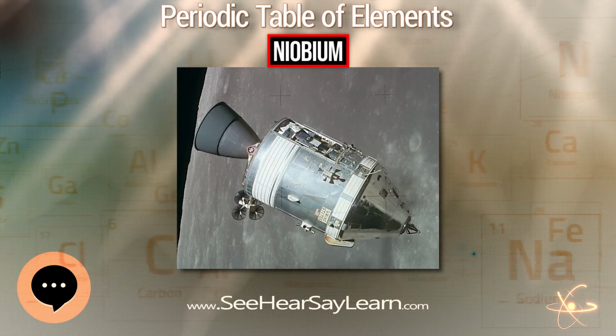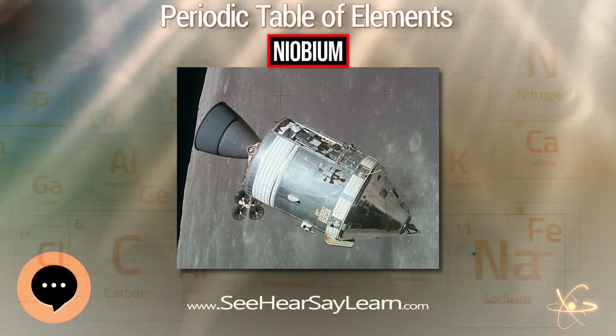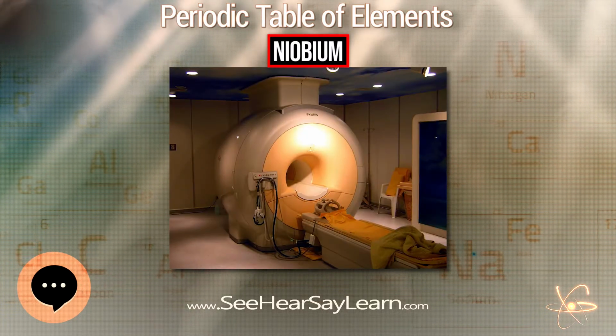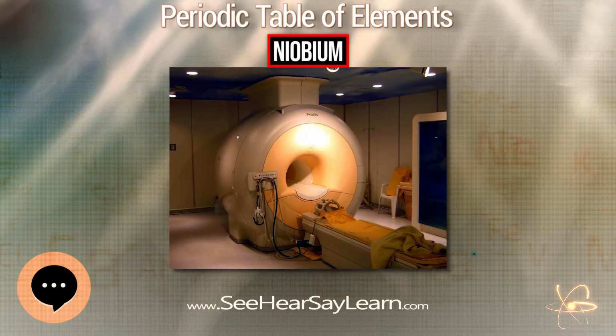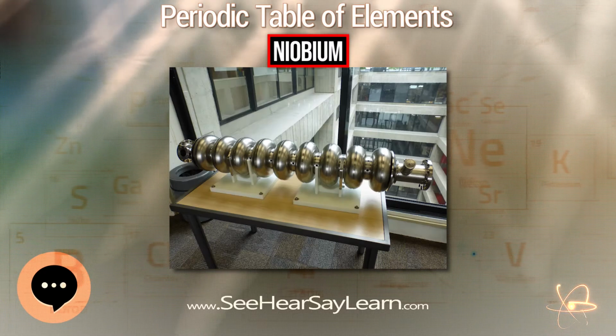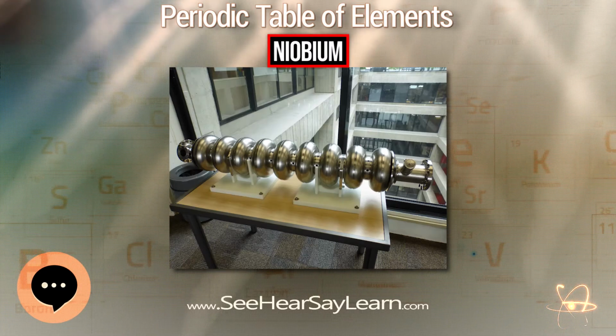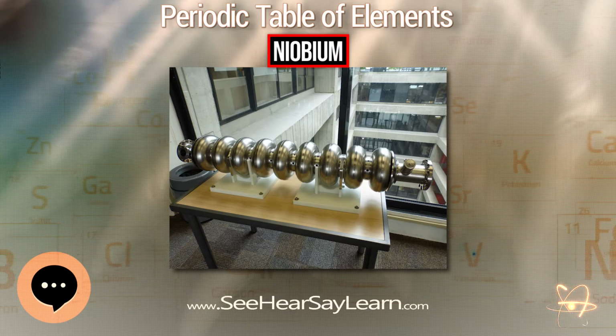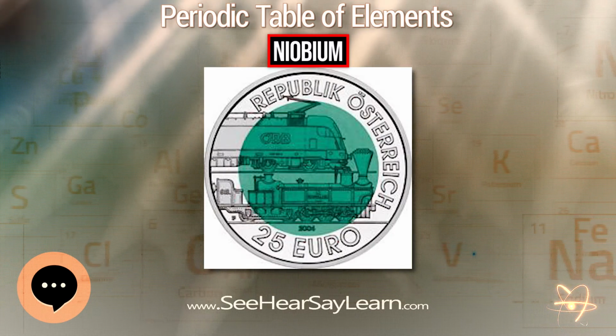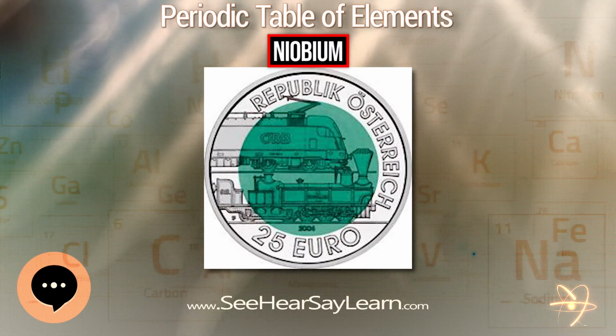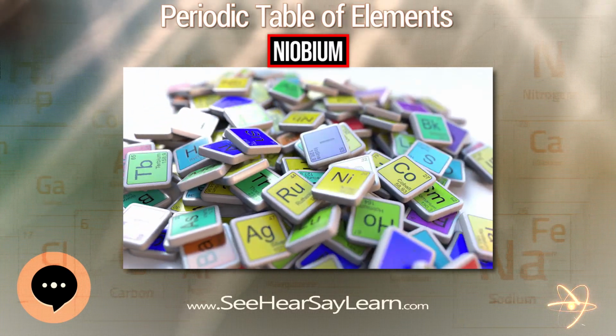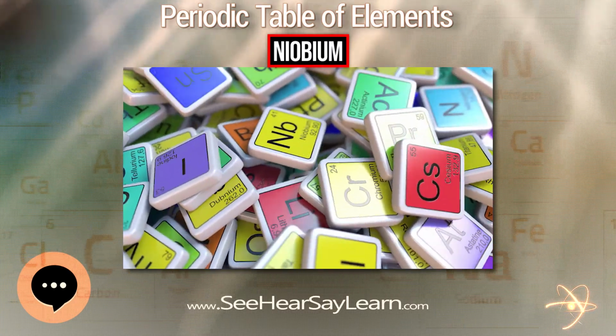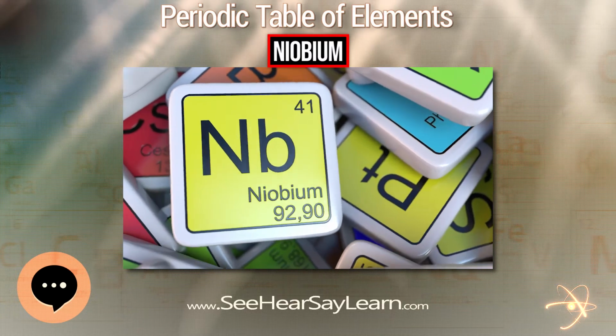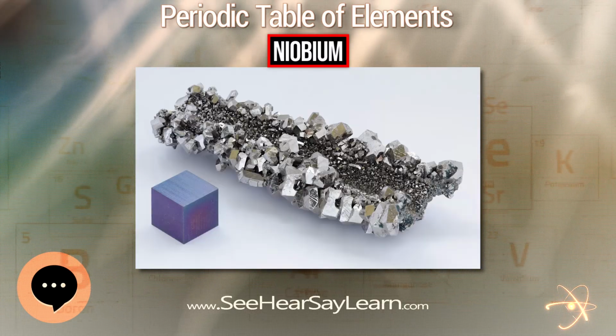The short and long-term exposure to niobates and niobium chloride, two chemicals that are water-soluble, have been tested in rats. Rats treated with a single injection of niobium pentachloride or niobates show a median lethal dose between 10 and 100 mg/kg. For oral administration the toxicity is lower. A study with rats yielded a LD50 after 7 days of 940 mg/kg.